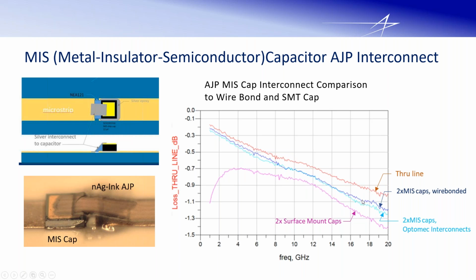So we're thinking on this third iteration, it's going to get even better than this, and it allows us to start putting these into our products, and we can print it along with a number of other components, and shrink the print down, eliminate the tuning. Because typically when you do wire bonding, you have to kind of tune the wires to get rid of the resonance. So you eliminate that.